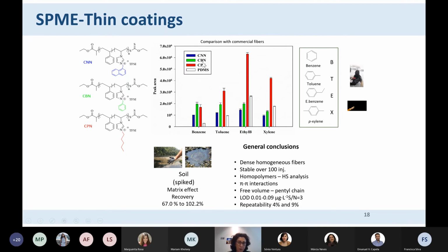So we are again comparing our fibers with commercial fibers in white, PDMS, again, polymer with polymer. This is a very well-known mixture, BTEX. And BTEX is typically tested to know if the soil is contaminated by gasoline or by fuel. And this is why we used soil. What we can see here is that, in fact, we are doing also much better than the commercial fiber that we compared to. The one that has the alkyl group was the better one.